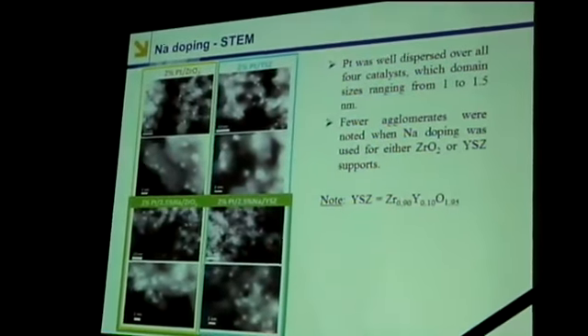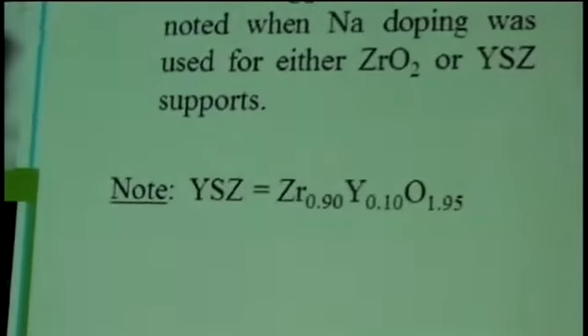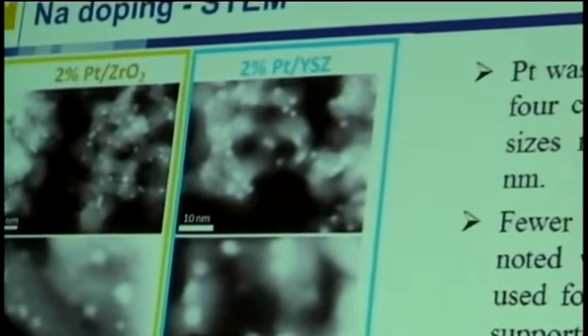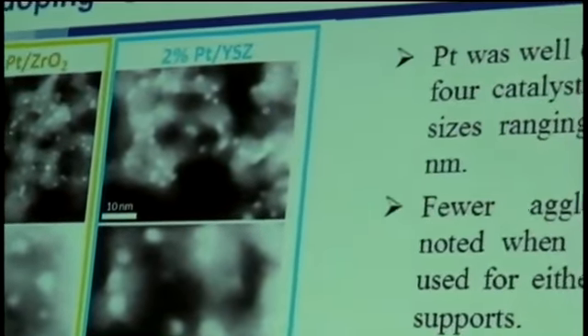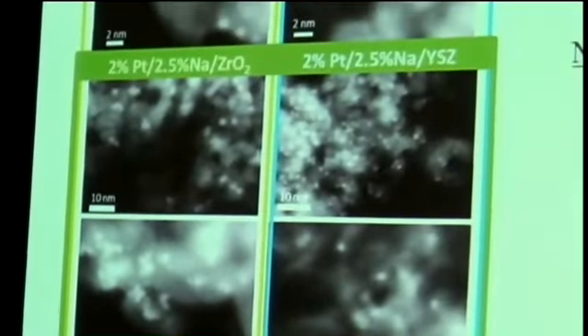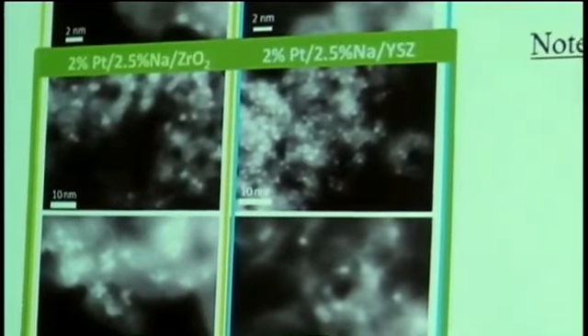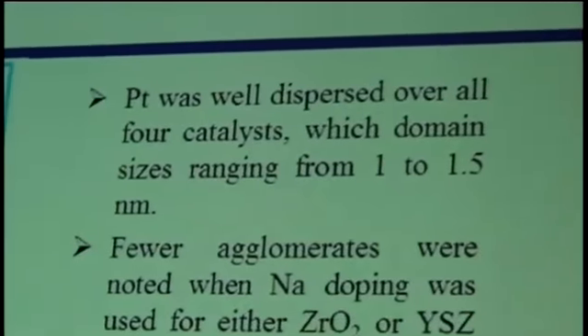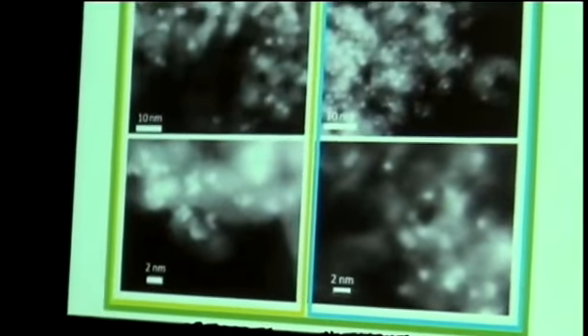Okay, let's look at sodium doping now, which is quite different. Here we prepared catalysts with 2% platinum, similar to what we had done previously with the work with Honda. Here we have zirconia, yttrium-doped without sodium, and here we have TEM images with sodium. And you can see here that without sodium, even though the domains on all catalysts for platinum range from about 1 to 1.5 nanometers in this case, we do see some agglomerates of domains without sodium, whereas here, the particles are more dispersed.